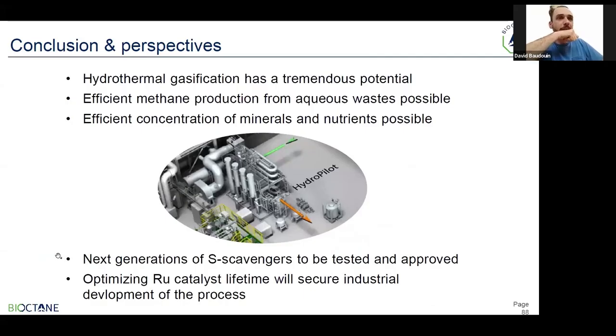And I'm coming to an end. So in short, I hope I've convinced you of the good and nice potential of hydrothermal processes in general, and gasification in particular. But I have also outlined some challenges that are faced with regard to developing catalysts in this field. Now, ruthenium on carbon is a star when it comes to the production of methane. When it comes to the production of H2, there will be a lot published in the coming years from us, hopefully, for the selective production of hydrogen. And we have to shift away from ruthenium, which is too selective towards methane. Some of the strategies that we follow are selectively poisoning or doping it, and using different new supports.